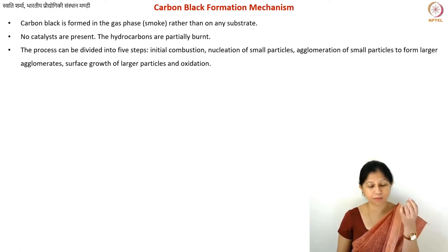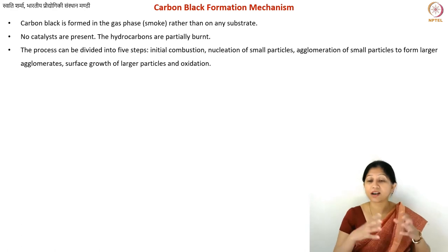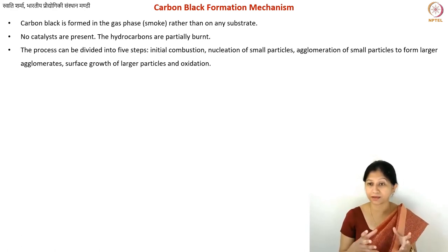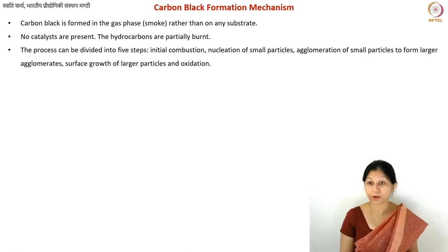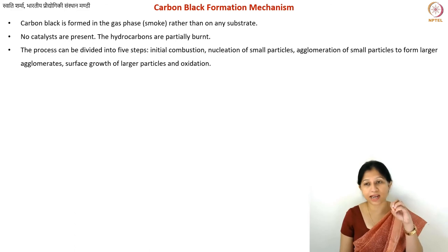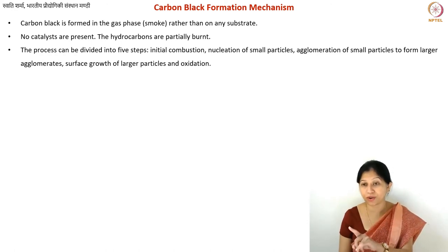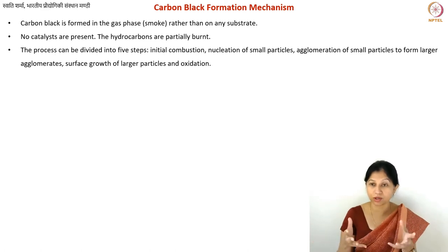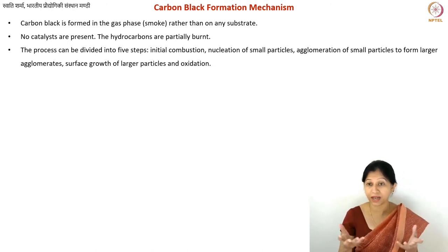The second step is nucleation and growth. Already you get nanoscale particles starting to form. Once you have large enough particles — which happens pretty fast, within seconds — these particles start to agglomerate. This agglomeration is a very important step. If you suddenly quench or change the conditions inside your reactor, you can stop the agglomeration at a certain point. You have nucleation of agglomerates and then surface growth, where more and more nanoscale particles attach to the same cluster. Sometimes you can even have large chain-like clusters.